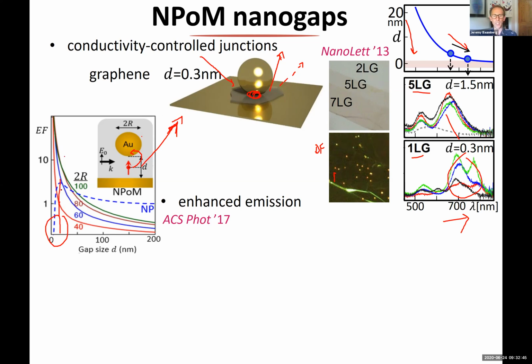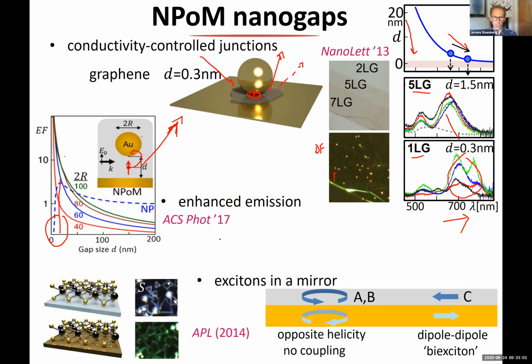So it's completely opposite to the normal nanoparticle. And it's the intuition that most people have for metals. If you bring a chromophore, an emitter close to a metal, then it quenches. And that's definitely not what happens here. We can see emission from chromophores which are within 0.5 nanometer of the gold. And they can be very strong. And I'll show you that.